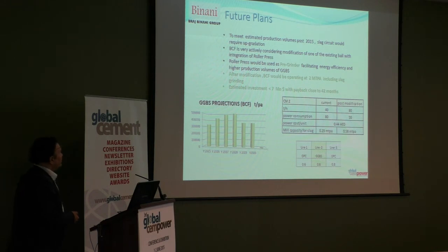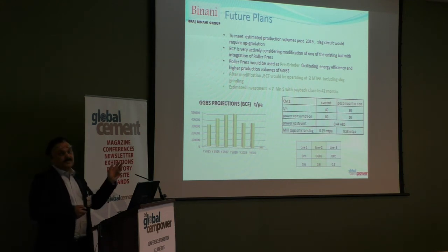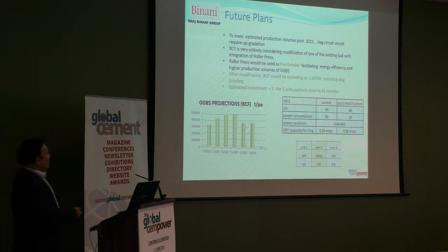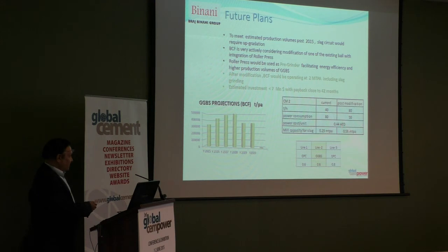So everything has a limitation. We did quite well in terms of swapping of power, but then you have a limitation. If you have to produce more slag, something close to 500,000 tons, then there is a limitation. So this is what we aim to produce in the year 2017-2018. This is the time when all these events will be having their peak consumption, either Expo 2020 or World Cup in Qatar. So the best solution which we have found and very seriously we are considering is that one of the mills will be converted, or we will install a grinder in one of these mills. So straight away that 40 tons becomes 80 tons per hour.